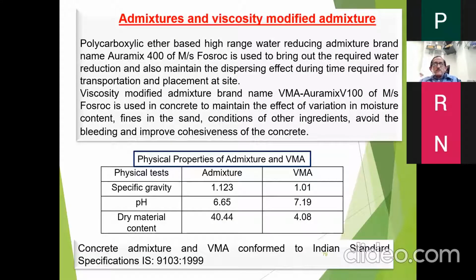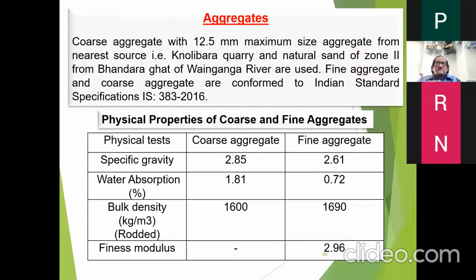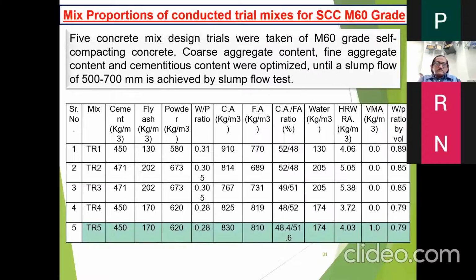Then a polycarboxylate ether-based high-range water-reducing admixture, Fosroc brand, was used. The viscosity modifying agent, VMA, was Auramix V100, and Auramix 400 was the hyperplasticizer, or high-range superplasticizer. These are the specifications with pH and dry material content as required per Indian standard 9103. And coarse aggregate was 12.5 maximum, so this was the maximum size, 12.5.